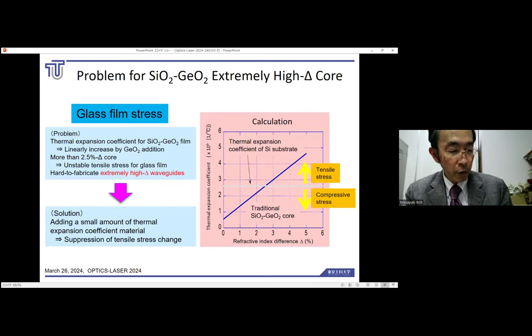For core films with a refractive index difference of 2.5% delta or higher, the glass film becomes unstable due to tensile stress, and there is a risk of film delamination, which makes it difficult to fabricate extremely high delta waveguides. Therefore, to solve this problem, the tensile stress can be suppressed by adding a material with a small coefficient of thermal expansion.